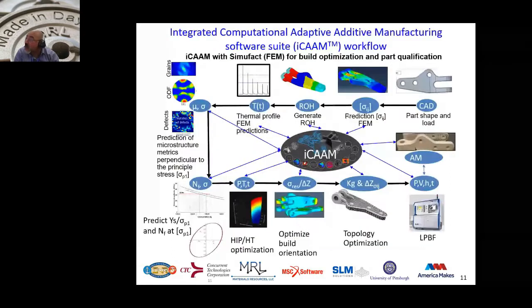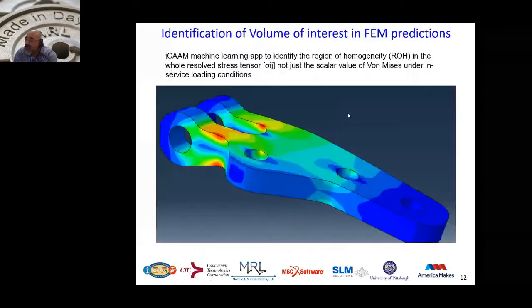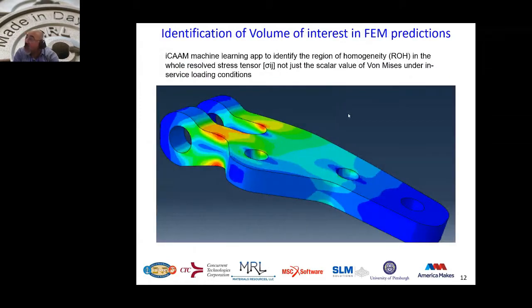Now this is the outline, and the first thing, as you see in slide number 12, is that we identified the most critical region under the in-service loading condition, which we define as the region of homogeneity. And here we looked at the whole stress tensor. It is the 3x3 stress tensor, and not just the von Mises value. And with that, we have a machine learning tool to identify the region of homogeneity based on the whole stress tensor. And it is generic, therefore it can be used in other parts generically, not just this part.